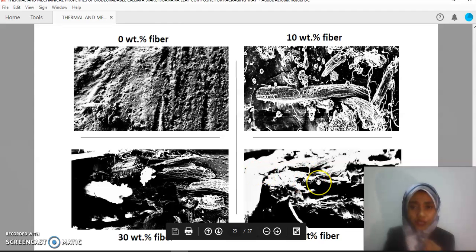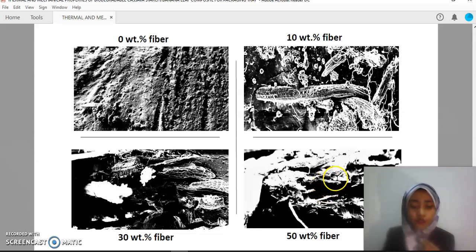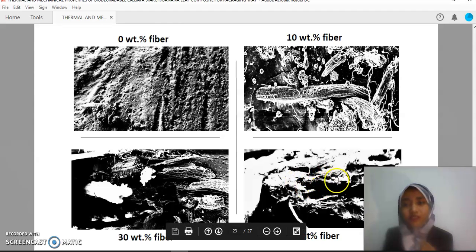However, at 50% fiber content, we can see agglomeration of the fiber because the matrix is insufficient to cover the fiber, so the fiber agglomerates. So it supports the tensile test result, which is that at 50% the strength is reduced.